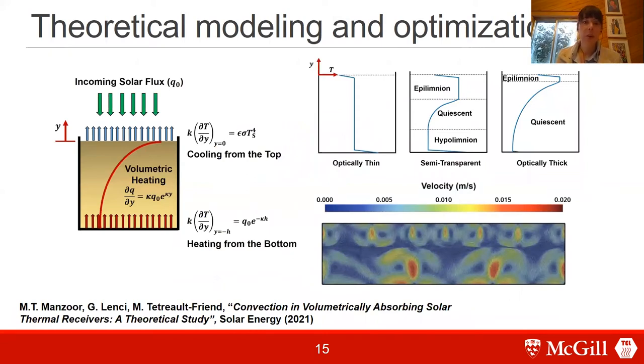So recently in my group, we developed a theoretical model that's able to predict the thermal behavior of a volumetrically heated molten salt. And we were able to predict three different operating regimes for the receiver as well as some complex flow patterns. And so we identified these three regimes and which one would be the ideal regime to be operating in for the solar receiver. And then this model will allow us to optimize the design, because it's very fast. So in terms of real-time computation speed, it can enable digital twinning for volumetric receivers, meaning that we can use the model to actually control the position of the divider plate, so automate that whole process.